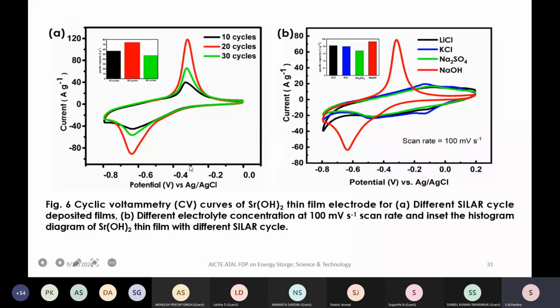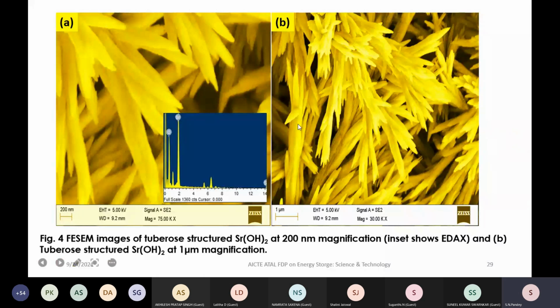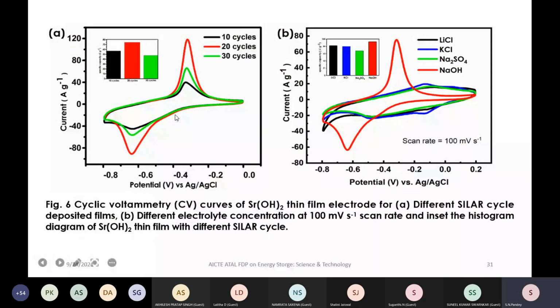First of all, we have taken the cyclic voltammetry curves for the 10 cycle. For 10 cycles, one can see at a scan rate of 100 mV per second, the covered area is very small. When we go to 20 cycles, one can see that the covered area has increased. We expected that if we go to 30 cycles, it would increase again, but one can see that it is not increasing, it is decreasing. Why is it decreasing? One can get the answer from here. Many tuberose structures have been developed, and these tuberose structures are going to cover the surface area, so the surface area is going to reduce. So one has to optimize the number of cycles. Once we have optimized the number of cycles, then we have to decide what electrolyte to take.